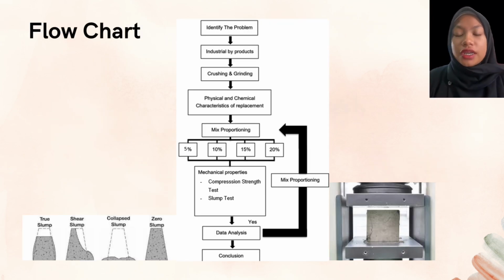So for the flowchart, firstly what we need to do is to identify the problem. So the problem is the shortage of sand. So we industrialize a byproduct, which is Pila Ampullacea. Then we crush and grind the dry shell of Pila Ampullacea, and we do a physical and chemical characteristic of replacement of Pila Ampullacea. Then we do the mix proportion. We use 5, 10, 15 and 20 percent. Then we do the mechanical properties by compressive strength test and slump test. Then we wait for 7 and 28 days.